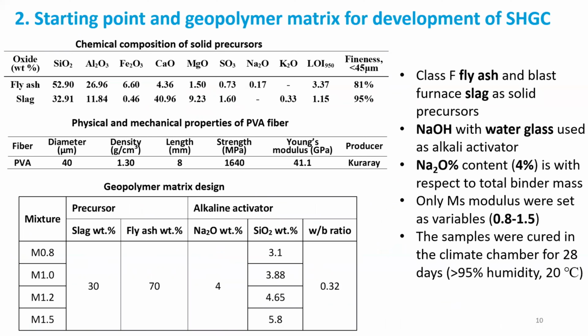So we use slag and fly ash for the matrix, and sodium hydroxide and sodium silicate solution as alkali activator. We actually fix all the parameters except for the silicon modulus, because we found that the matrix and the interface properties are quite sensitive to the silicon modulus. We cure our samples in a climate chamber for 28 days before testing, and the PVA fiber was used for the composite and also single fiber pull-out tests.